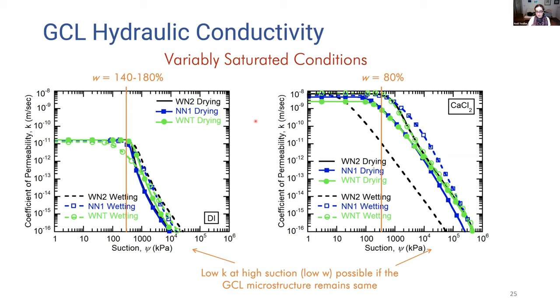And this is actually something that we observe in the field when we are dealing with some of the highly dried up materials, materials with very low moisture contents. We see that some gaps have opened. There are some macro cracks within the bentonite structure. And these relationships, again, probably are not directly applicable to those cases. And if you're going to use such relationships, caution is something that's good to keep in mind.